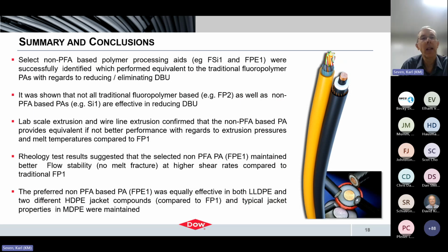So here I'm just going to summarize what we conclude from this work. I think the big picture is that obviously the fluoropolymer-based processing aids perform very well, in particular for reducing die-lip buildup. However, if you can select non-PFAS-based processing aids, they will work equivalently, and in some cases perform slightly better, at least within the context of this study. We identified one in particular that performed extremely well compared to the typical fluoropolymer additive. I'll highlight that these processing aids do need to be carefully selected, depending on what problem you're looking to solve.